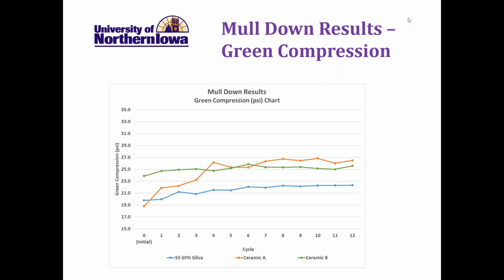What we're looking for here is the bond development. We know the longer we mull sand, the higher the properties will be. But that rate of increase in properties gives us a measure of how well that material is going to develop strengths. We can see that both the ceramic samples mulled in with higher values faster than the conventional 55 GFN silica sand did.